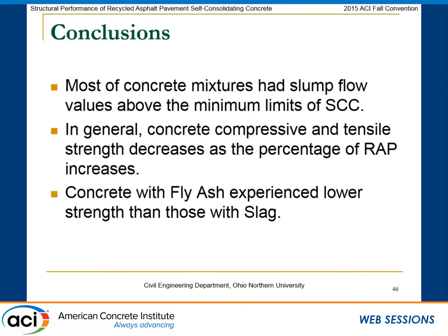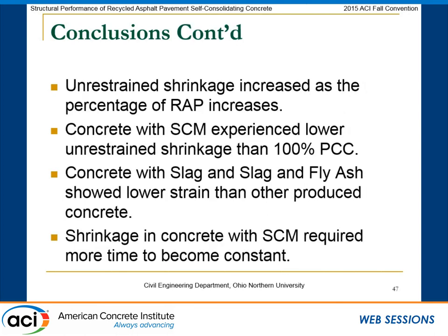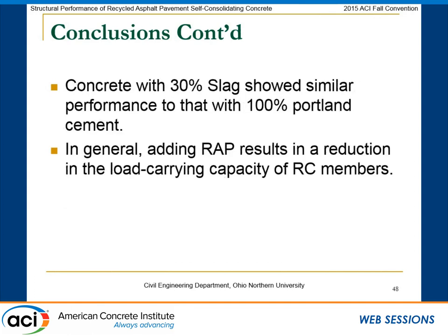In general, here for conclusions, we were able to produce SCC using RAP. And as you increase the amount of RAP, your concrete compressive strength and tensile strength would decrease. Concrete with slag showed better behavior or more strength than the fly ash. And for unrestrained shrinkage, as you increase the RAP, the shrinkage would increase. And concrete with the SCM experienced lower strain, lower shrinkage than 100% Portland cement. And concrete with 30% slag and also with 70% slag showed similar performance to the 100% Portland cement.